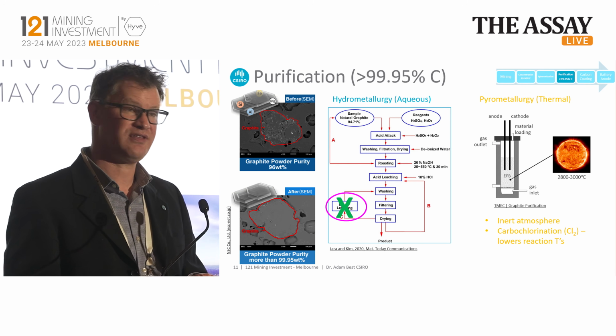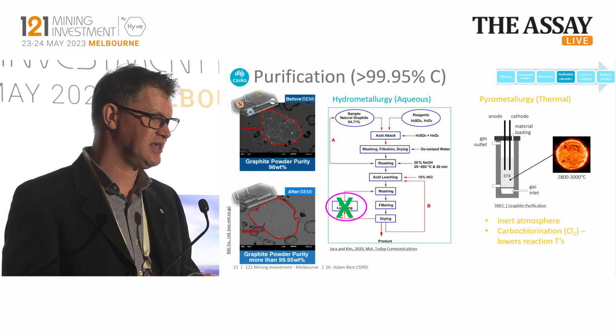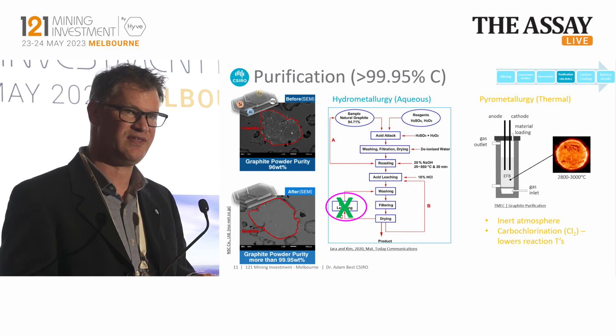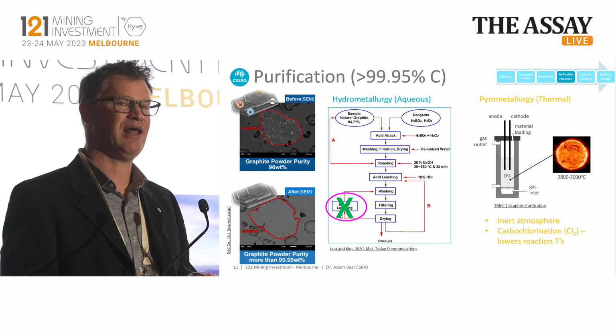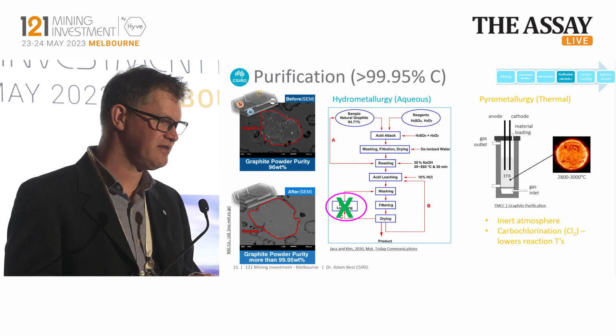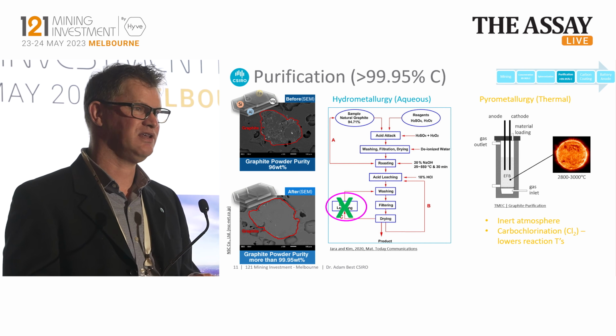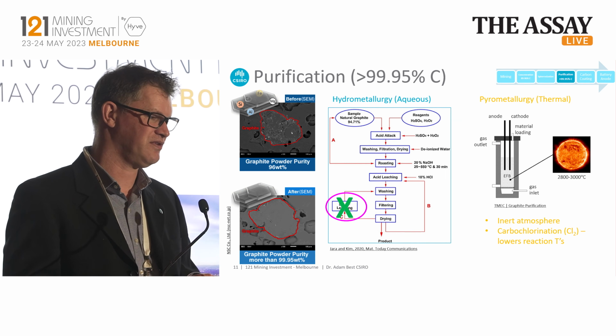There's also another step you can use, pyrometallurgy. Basically, you can heat this up to 2,800, 3,000 degrees Celsius and basically melt out the impurities. Graphite's great because it'll just regraphitize itself at that temperature, so you won't actually lose anything there, so it's quite useful.